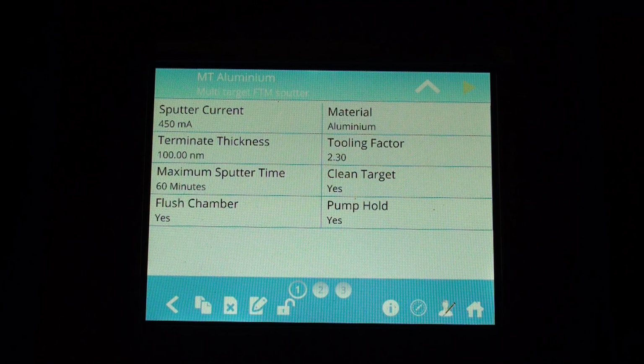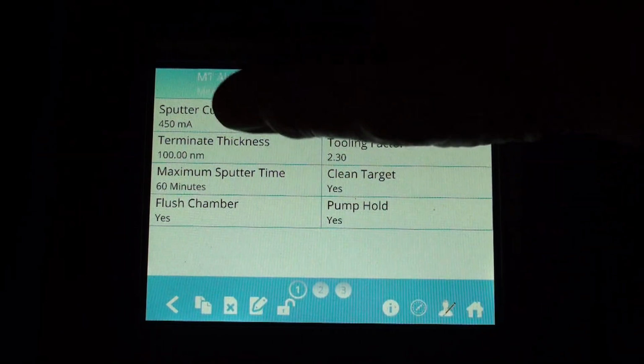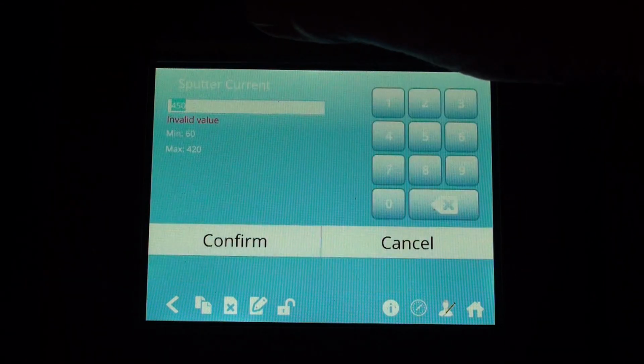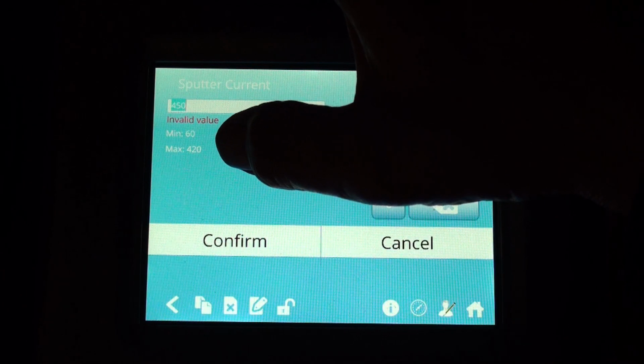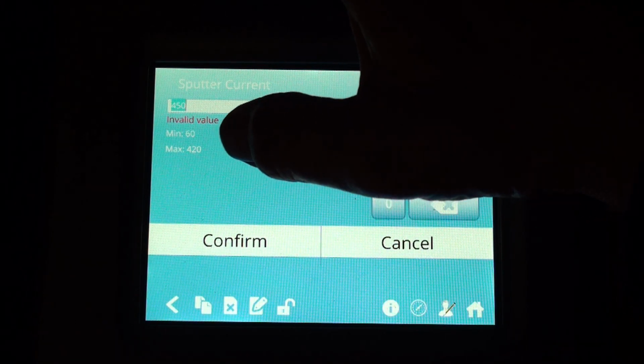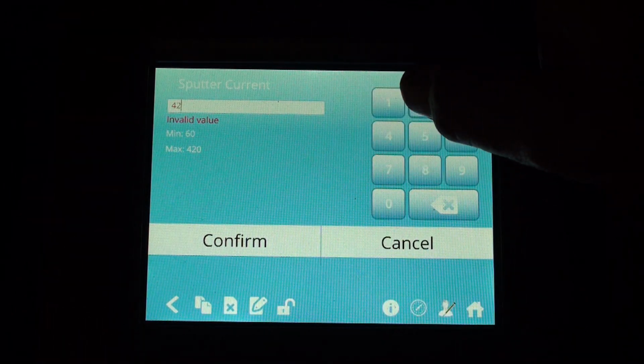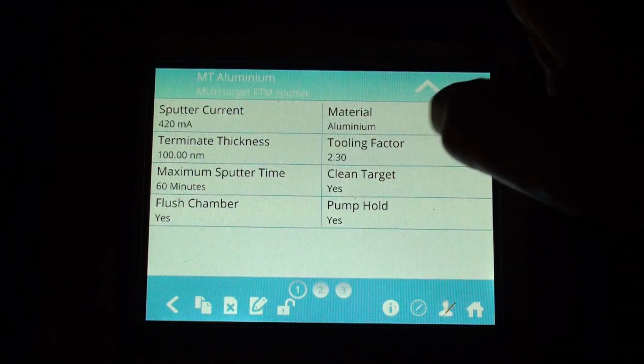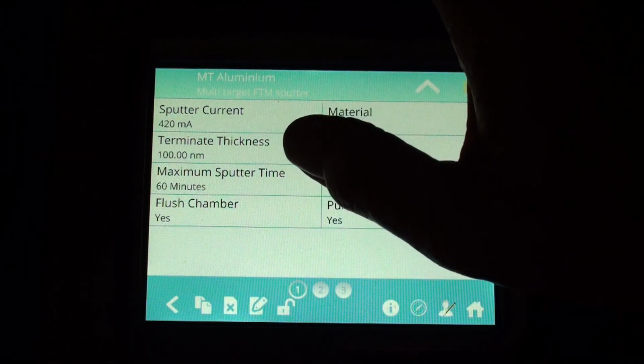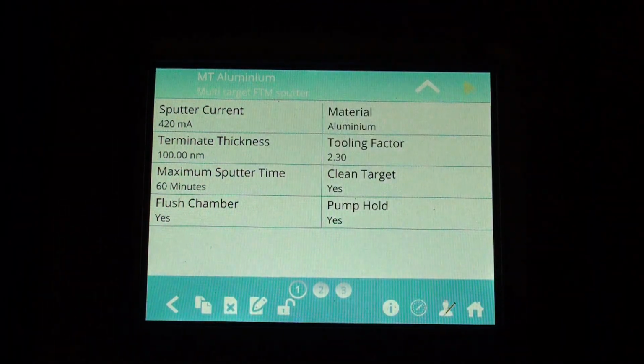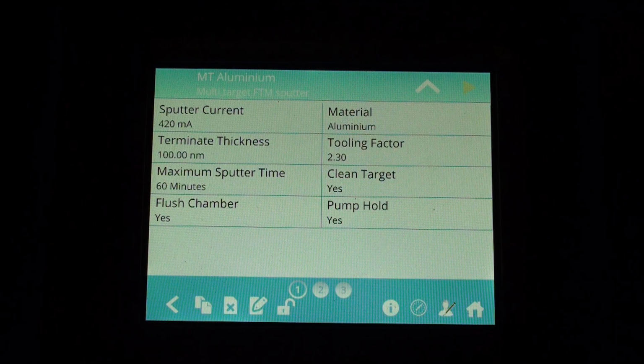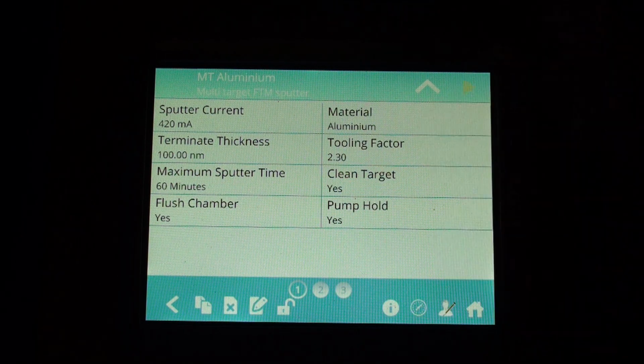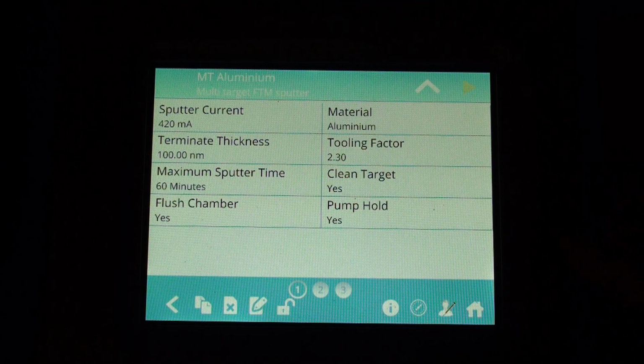This one was set up for 100 nanometers of aluminum, but you can set the termination thickness to what you want. We brought it up to one of the highest values of sputter current we could, which the max is 420. Maximum sputter time is 60 minutes. Flush chamber, yes, you want to flush the chamber because you want to flush out as much room air as possible. Once you get in there, tooling factor we're not going to deal with.